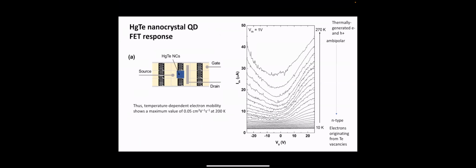So what we're really interested in are their optical properties. So they behave as an ambipolar transistor. So at room temperature, you see both N and P type response. And then when you cool the particles down, you end up seeing N type response. And so that is electrons originating from tellurium vacancies. So sometimes we'll do these FET measurements on nanocrystals prepared with different ligands just to get a sense of how many vacancies are being created and things like that. So you can see that sort of thing from the FETs.